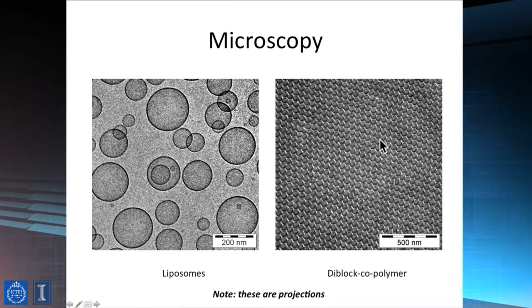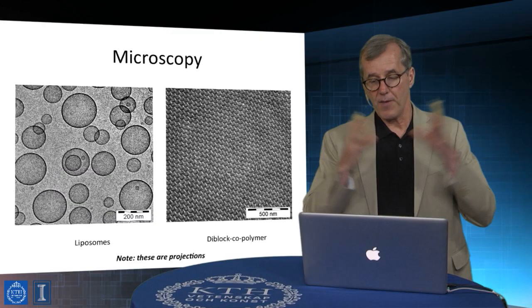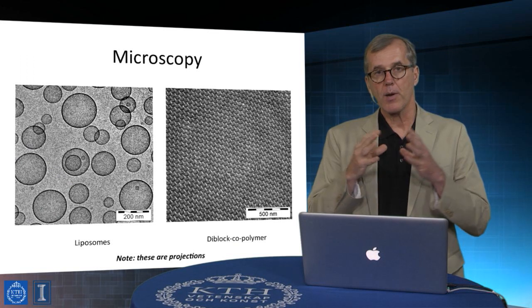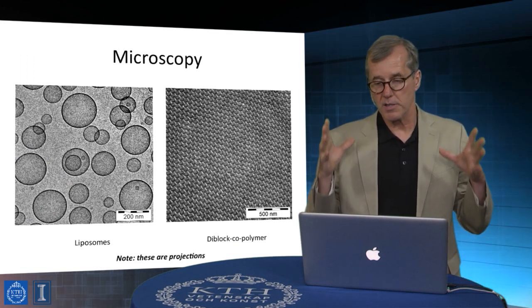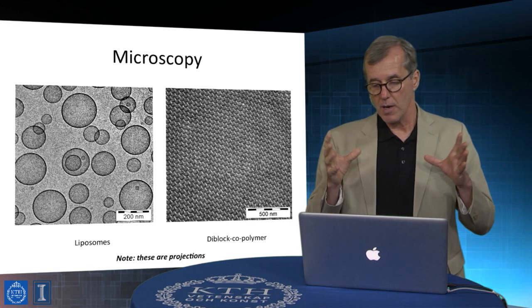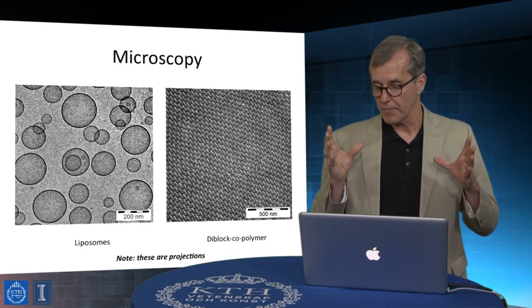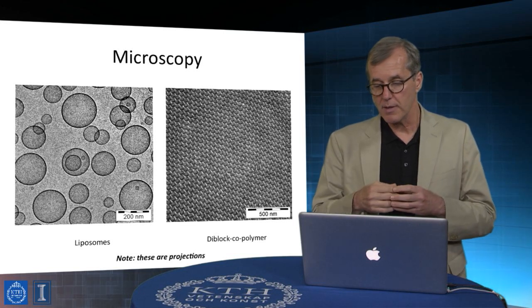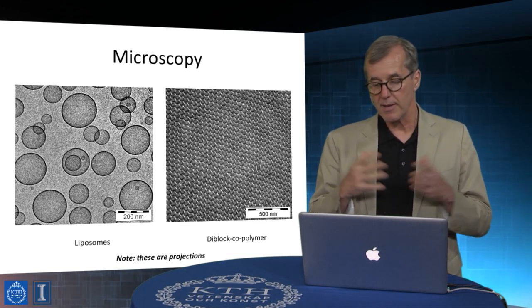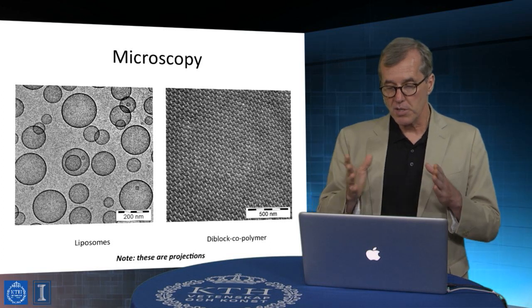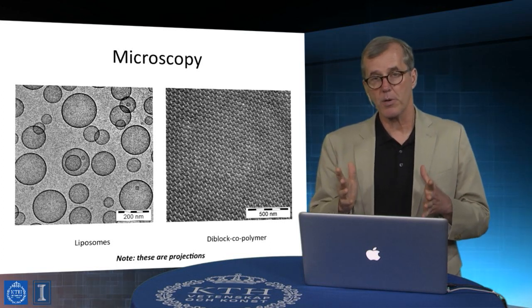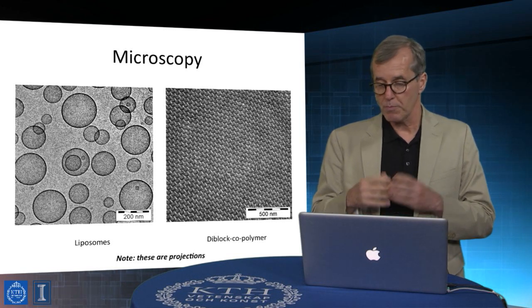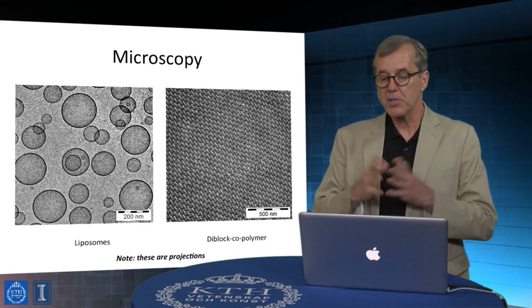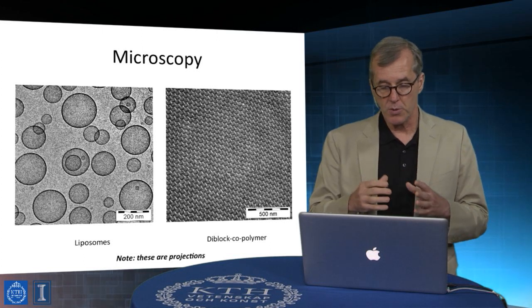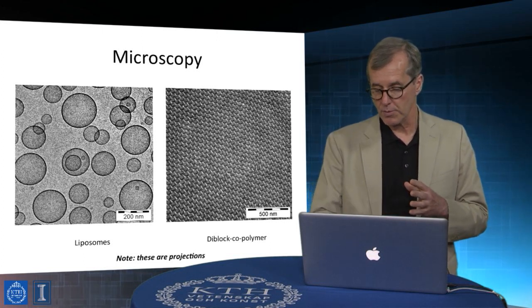And basically what's reflected in that second case is the fact that polymers have phase separated, but they can only phase separate at distances of the order of the domain size of a specific block. So the length scales are very small in this case. They're at the nanoscale, and because these diblock copolymers are very monodispersed, you wind up with beautiful long-ranged mesoscopic organizations that are possible to induce with these kinds of materials.